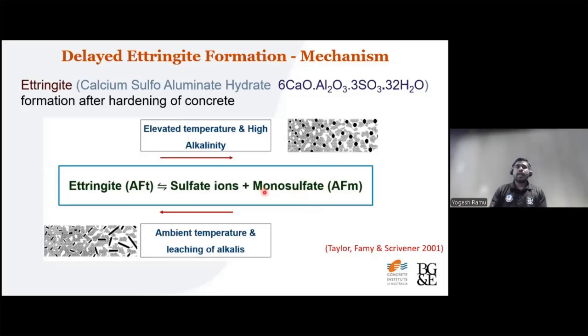I will just take the laser pointer to point this out. The black dots in the graphical representation that you see in the slide represent monosulfate. What can happen is that during the service life, when the concrete temperature is back to normal, and when there is a favorable situation for the alkalis in the concrete to leach out from the system, say for example exposure to water, this monosulfate can react back with the sulfate ions to precipitate ettringite back in the system. This is happening after the concrete has hardened enough, during the service life.